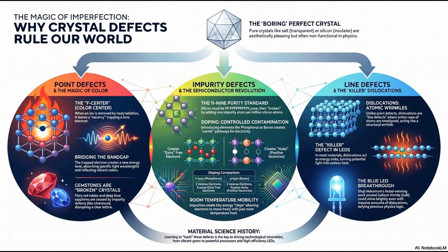And what did they find? The answer is one of the most elegant paradoxes in material science. Okay, walk me through it. How did the worst material ever made produce the brightest light? It turned out that the specific chemical nature of the alloy Nakamura used, specifically adding indium to create indium gallium nitride in the active light-emitting layer, created a secondary effect that neutralized the killer defects.